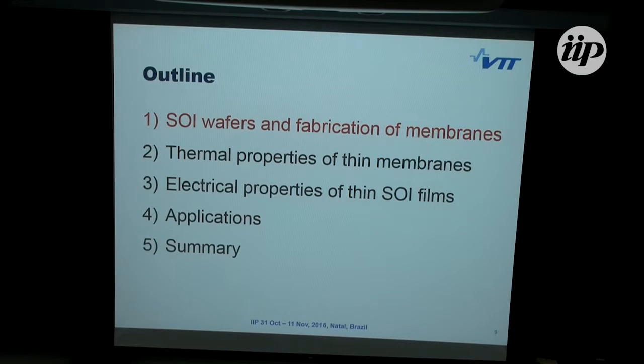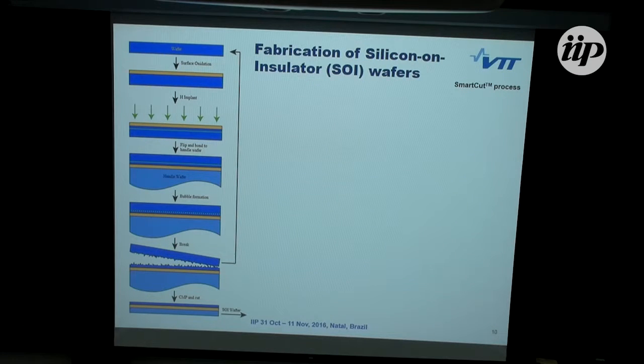So, SOI wafers and fabrication of membranes. Silicon on insulator wafers, I would say 90% of computers are using these SOI wafers. And here is the fabrication process. We start with a bulk silicon wafer, put some oxide on the top, and then a high dose hydrogen implant, so it has a certain distribution inside the wafer. Then this wafer is turned upside down and bonded to a so-called handle wafer, and then this is heated up. So there are two things. The interface is healed, so the wafer bonding takes place, but then the hydrogen starts to form bubbles inside, and then they break the wafer,